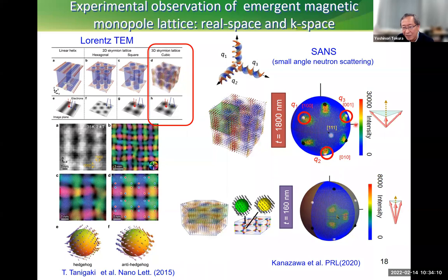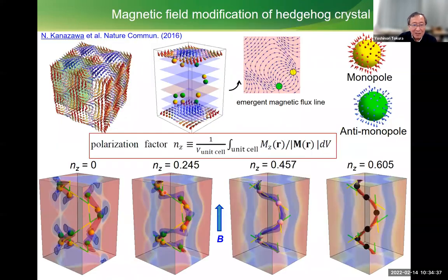The 3Q vector is exactly an orthogonal X, Y, Z direction when you build along the 111 direction. But importantly, if the thin film is rather thin and the magnetic anisotropy is strong, then this umbrella tends to close. But then we have another kind of hedgehog, anti-hedgehog, or monopole, anti-monopole crystals. And this monopole, anti-monopole pair crystal also showed a gigantic electromagnetic response.